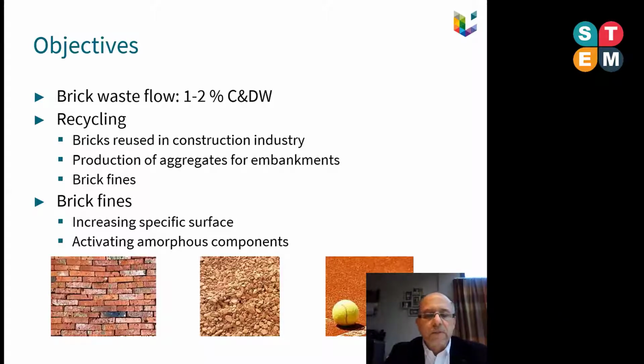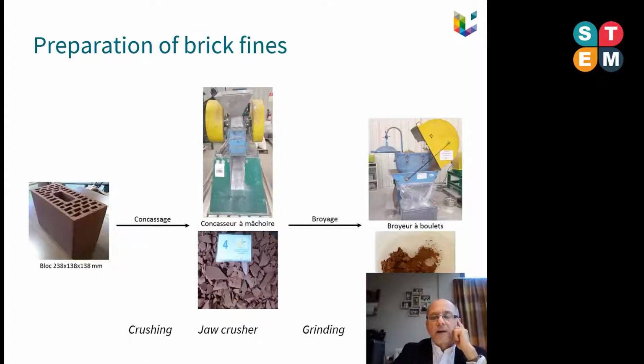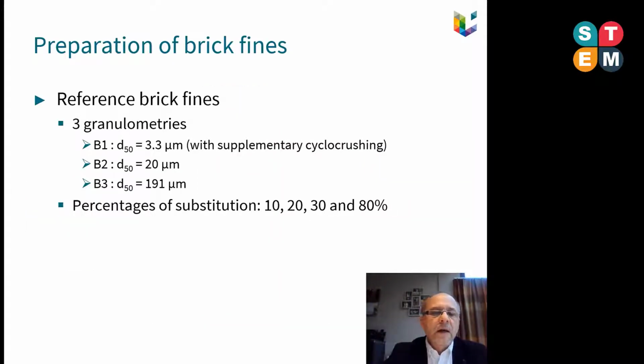The crushing of this brick is performed in order to increase the specific surface and to activate, by means of this fine crushing, the amorphous component of the material. That's what we tried to do by a classical process in the lab, crushing by means of a jaw crusher, and then grinding by means of another crusher. We obtain three types of granulometries, B1, B2, and B3, corresponding to very fine, classical, and coarser particles. The classical one, B2, corresponds to the dimension of classical cementitious particles, and we performed tests in order to study different percentages of substitution from 10 to 80%.